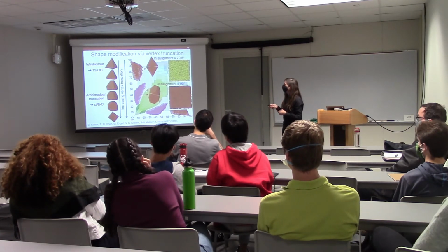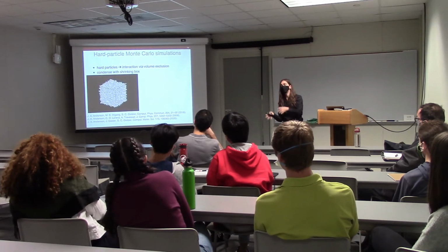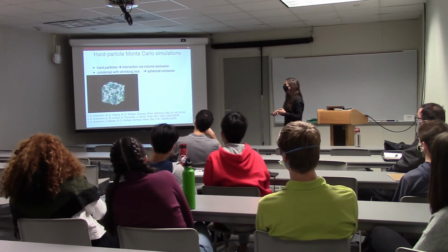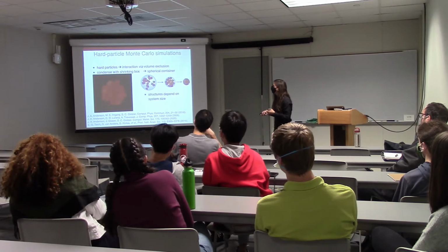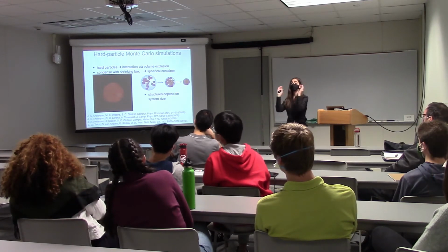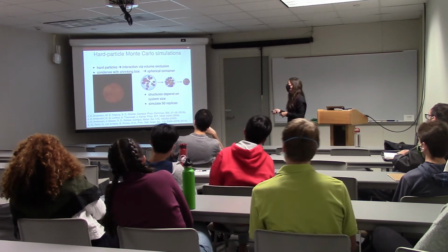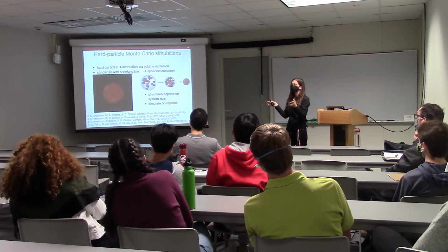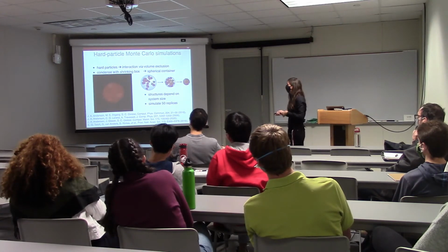That's the range that Rachel started investigating. Before, we were just shrinking our blocks with periodic boundary conditions and waiting for crystallization to happen. What we do now is we have a container that we're shrinking, and we're waiting for the particles to arrange in some kind of pattern. The structure depends on the system size, because the curvature of your container increases the smaller your system is. We simulated several replicas to properly sample the phase space, because at some point they get jammed where they are and nothing happens anymore.